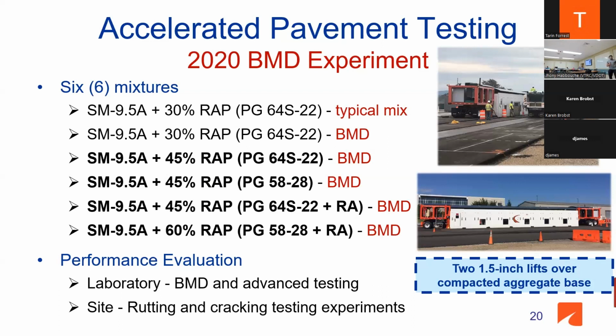So we have 6 lanes. We have the typical mixture at 30%, but we do have 4 mixtures that have 45%. We even made it up to 60%. We use several alternatives, whether we use engineered chemical additives that we call the RA, or we use a softer binder, that's the 4th bullet, or we use both together when we get the 60% RAP. We're currently doing the testing.